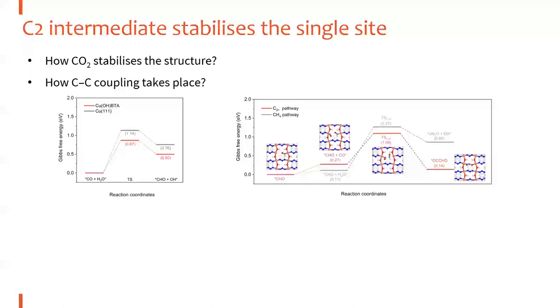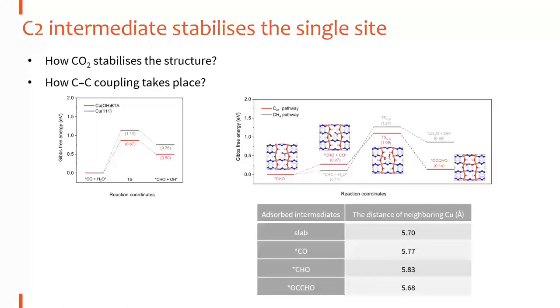But then how does CO2 stabilize the structure? To answer this question, we analyzed the copper-copper distance of the neighboring copper sites. We found that in the pristine molecule, it's around 5.7 angstrom, if you recall the number. With the sorption of CO, CHO and OCCHO intermediates along this reaction pathway, the copper-copper distance does not change considerably. That means in order to accommodate the intermediates for the reaction to happen, the structure does not need to undergo very severe change, so the material can remain stable. So there is no driving force for the material to change its structure and form aggregations.